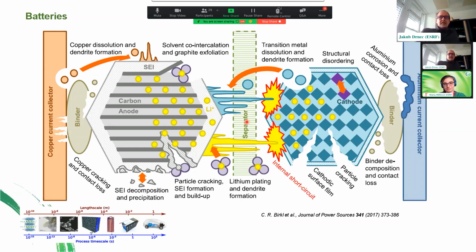So here, for example, we are talking about the anode side, right? So you have a graphite anode, the lithium intercalates in and out. As it intercalates, it's at very low potentials. That means that the electrolytes are not stable. So you make these interfaces. The interfaces, on the other hand, might not be perfect, and they can destabilize the whole structure, right?